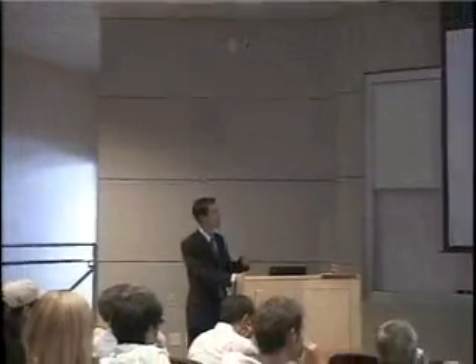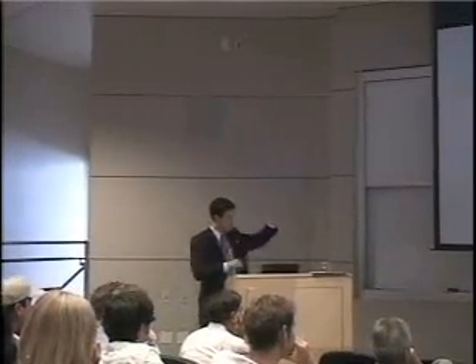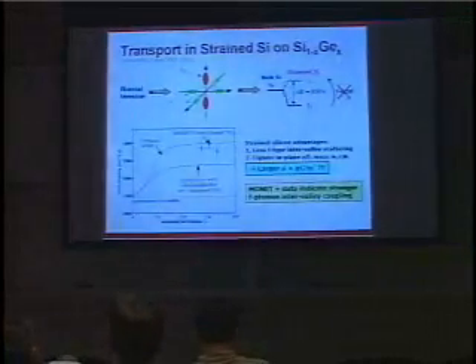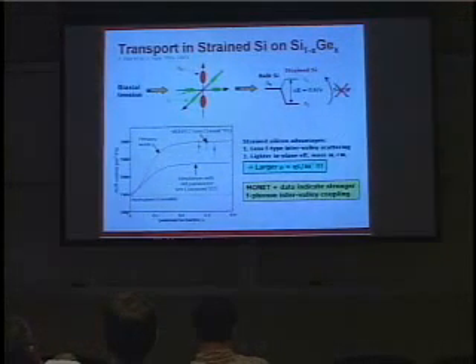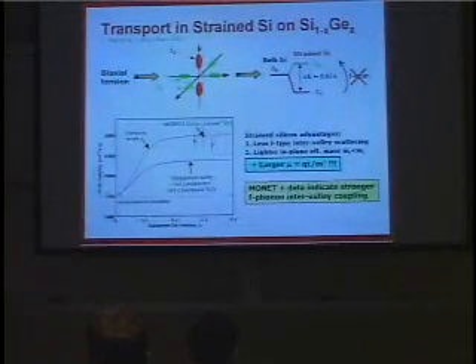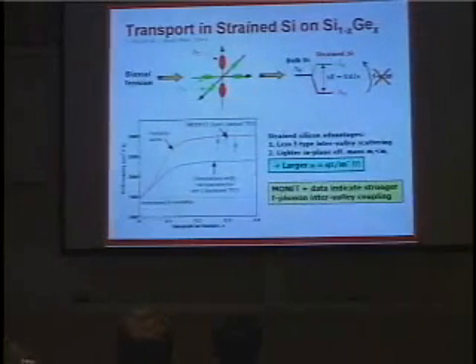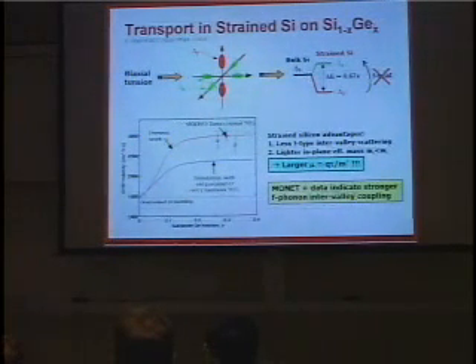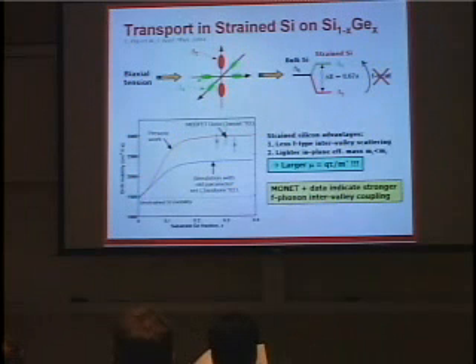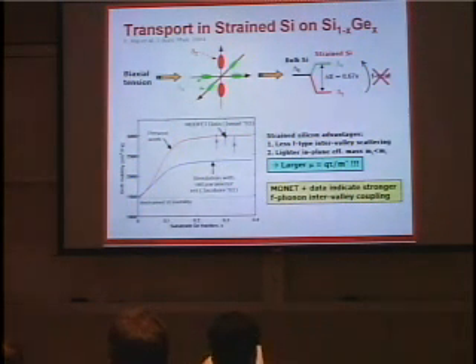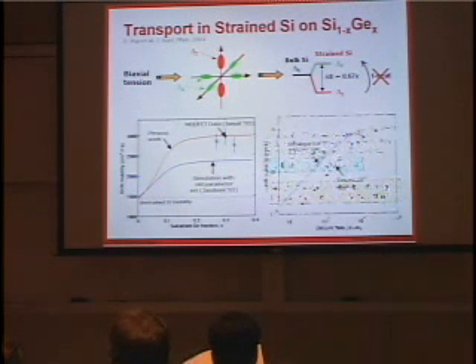The cleanest data that's available in the literature was done 10 years ago at IBM. So you see the mobility enhancement actually being modeled much better. And this basically indicates that there's somewhat less F phonon. I'm sorry, there's more F phonon scattering in silicon than people were originally thinking, because only if there's more phonon scattering, and then you're removing some of it, can we get the extra mobility enhancement that we're seeing.